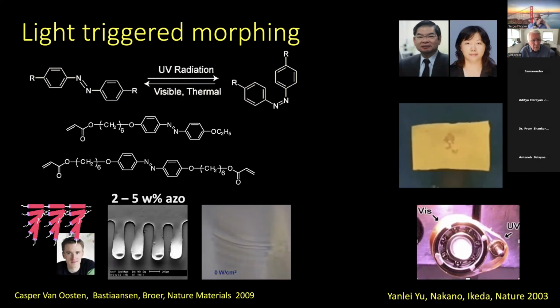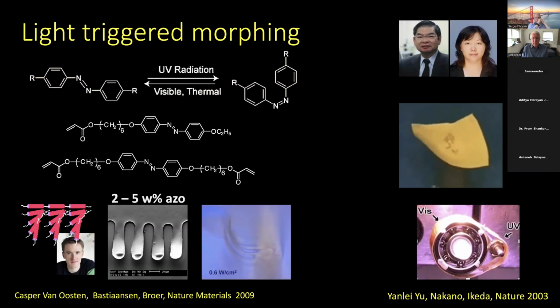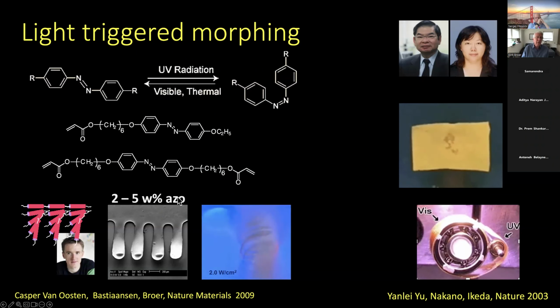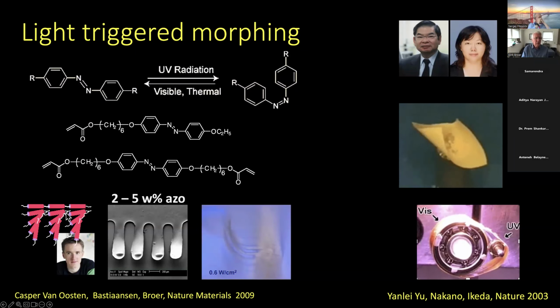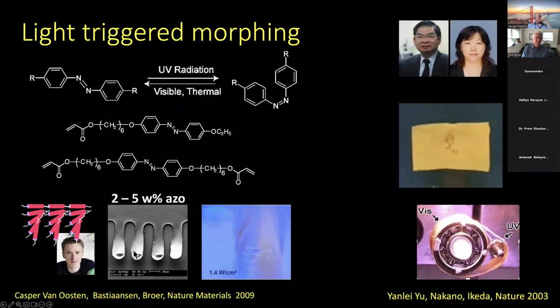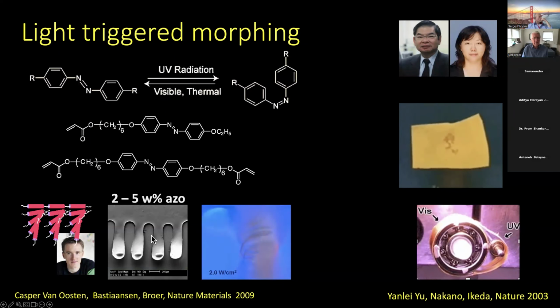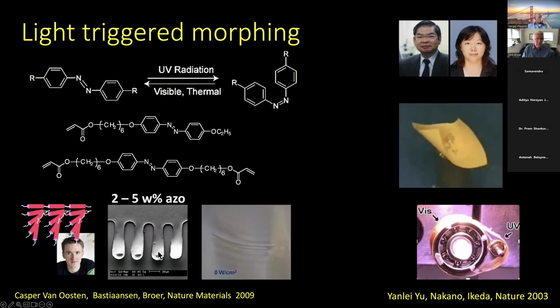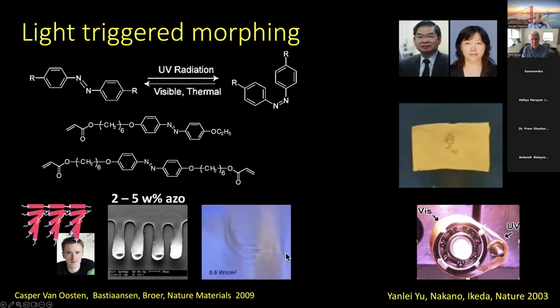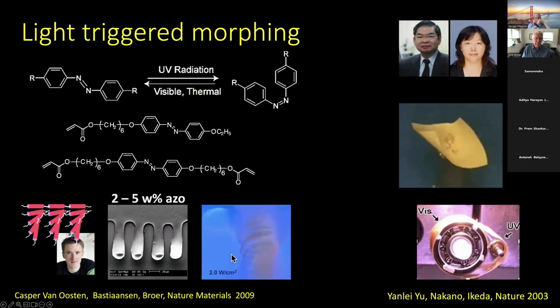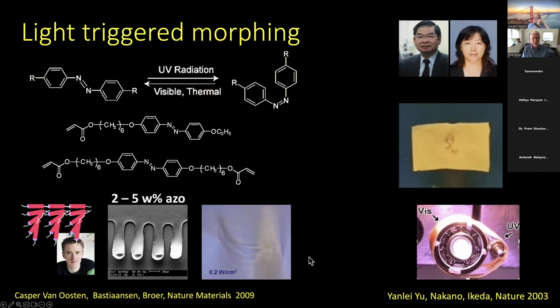Also in our group, we were working on that, and actually we found that we only need a very small amount of azo compound in the material to get already the bending properties. So this is the work of Casper. We inkjet printed the material in a splayed state, and then just by exposing it with UV light, the finger starts to bend. The movie is a little bit blurry because it is taken underwater to avoid photothermal effects, but the bending is obviously there.